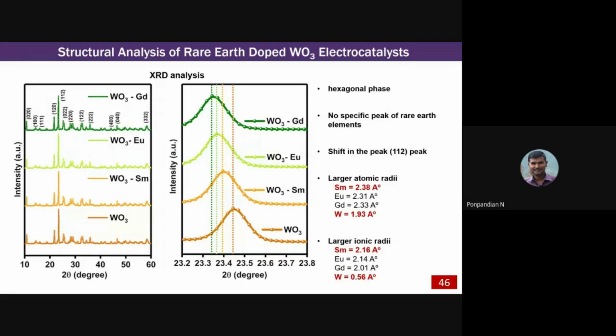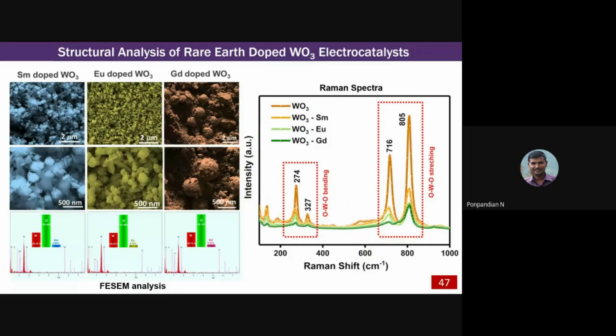These are the same characterization techniques which we performed for these rare earth doped materials. This is the morphology of the samarium, europium and gadolinium doped materials, and you can see the difference in the morphology. The morphology also plays a vital role when you are doing electrical characterization of the material, not only size. When you reduce the nanoparticle size, the catalytic activity changes, but based on the shape, the electrical property changes. In that way, you can see the electrical property changing here.